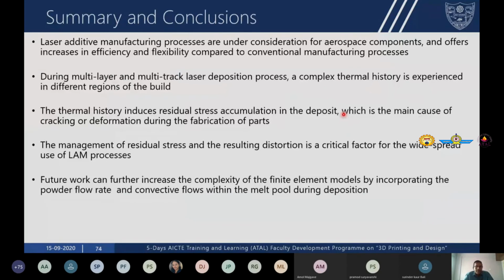So in summary, laser additive manufacturing processes are under consideration for aerospace components, and they offer increases in efficiency and flexibility when compared to conventional manufacturing processes. During the deposition of either single track components or multi-track, multi-layer components, a complex thermal history is experienced by the build because of the repeated heating and cooling cycles. This complex thermal history induces residual stress in the component, which is the main source of cracking, delamination, or distortion of the components.